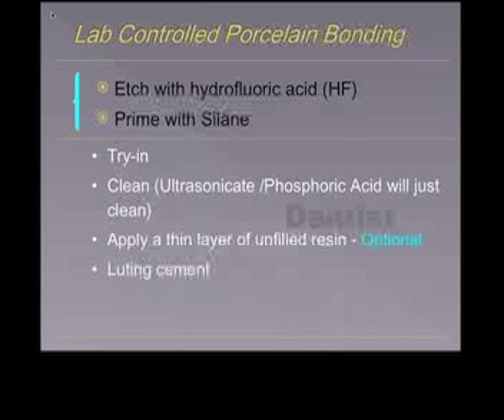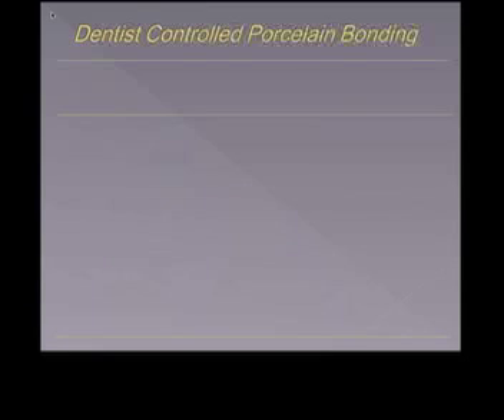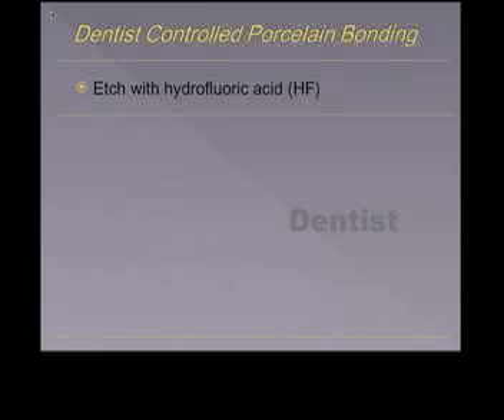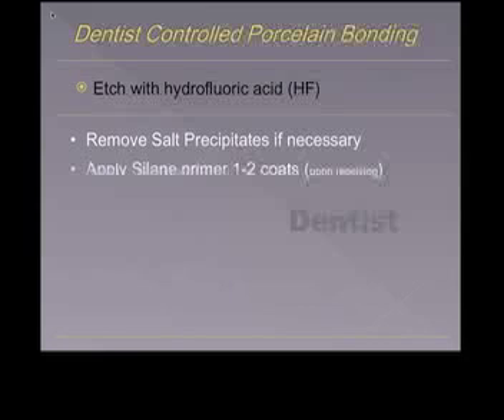Now, you want to note that in all protocols, it's ideal to silane the substrate immediately after you get it back from the lab, or at least prior to the try-in. This allows silane to interact or mature, in addition to forming a hydrophobic surface, which is less prone to contamination from try-in paste and salivary protein, and is also much easier to clean.